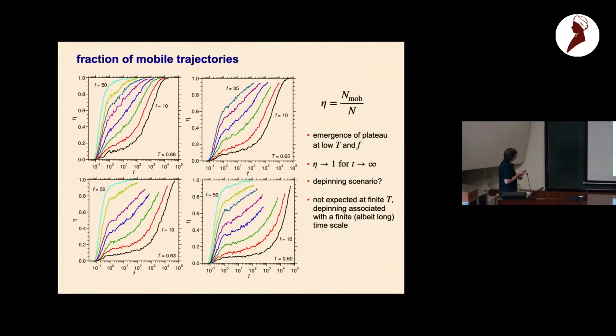Here are the results for different temperatures, most pronounced at the lowest temperature. We see that at low temperature and low forces, there's the emergence of a plateau, and we have to wait some time before it shoots up. Then all the particles become delocalized.